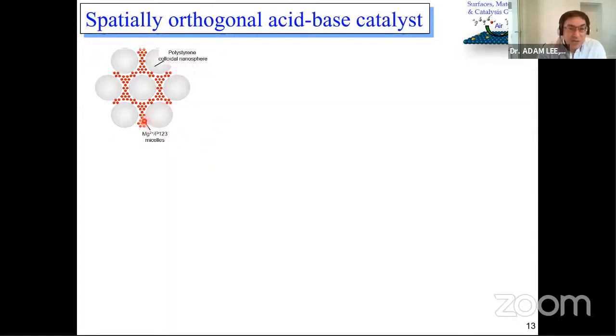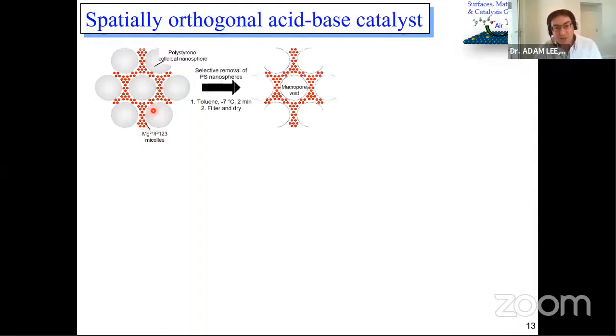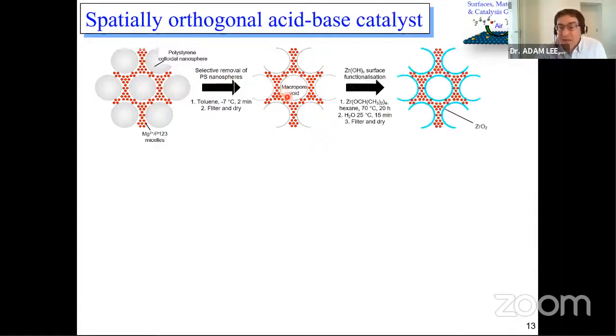Here we've got the red circles are our small templates, our surfactant templates. But this time we've put a metal ion into the surfactant. We've chelated it, bonded it to the surfactant. So even now at the starting stage, we have a metal phase present within these mesopores. We can now extract, just as we did previously, the large polystyrene templates to make an empty macropore. And we can then functionalize that.